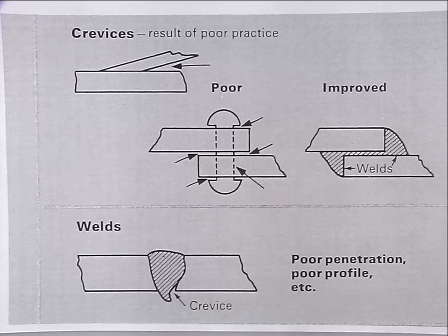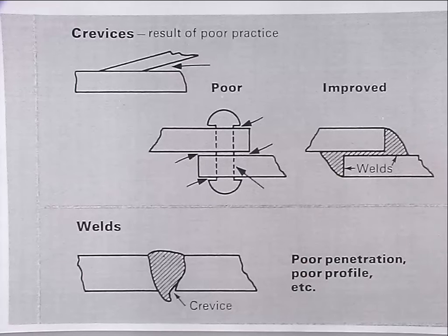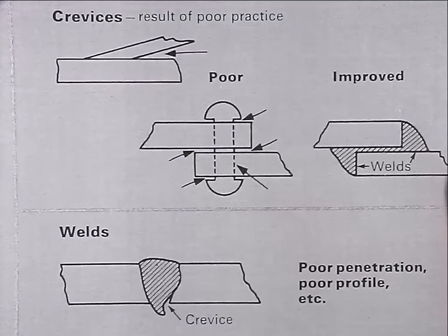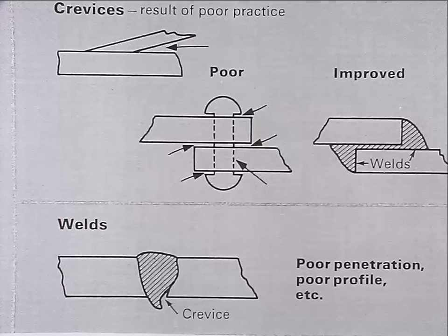Anywhere where you build a crevice into the geometry of your components, that's bad news. So overlapping plates riveted together historically in structures was bad news. The answer, of course, is to start welding things and put a fillet weld in to join the plates if they're going to be in an overlapped position. More likely it's going to be a butt weld, and that is a butt weld at the bottom here. The thing you have to be a little bit careful about with welds is that the root of the weld is of good quality. What we've got here is a little crevice being generated because there has been insufficient heat in the welding process, and you haven't got good weld penetration of the joint.